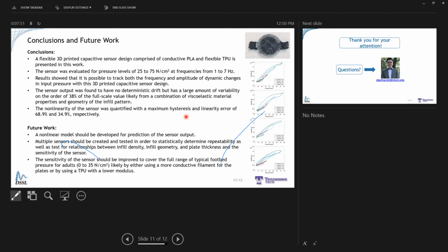Moving forward, we began testing and developing nonlinear models to help with the sensor's prediction output. And also we've been moving towards printing multiple sensors to determine the statistical repeatability for these sensors, and then test for things like infill density and infill geometry and its relationship to the sensor sensitivity. And then finally, in order to get to that goal pressure range of 0 to 35 Newton per centimeter squared, we are testing different filament types to see if we can get a lower modulus to help increase the sensitivity of our sensor.